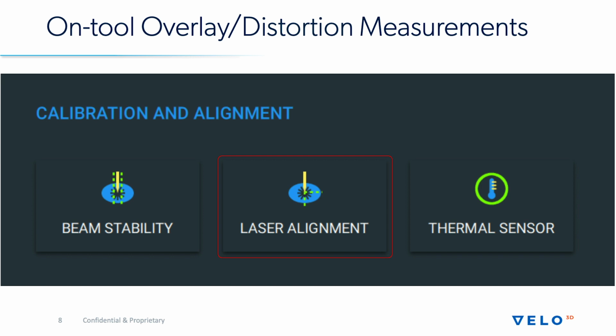So the Velo system comes built in with multiple different metrology and sensors that allow you to monitor different aspects of the machine health before you actually begin prints, to help reduce the scrap that comes from being off on any of these areas. This is an example screen shot from the print software itself. These are just buttons that you can press when you walk up to the system. We have buttons related to checking beam stability. So this is an automatic test to see whether or not the system has any thermal lensing and whether or not any optics need to be cleaned. We've got a thermal sensor test, which determines whether or not the melt pool alignment is proper with the coincident beam. And then finally, the one I'm talking about here is the laser alignment button.